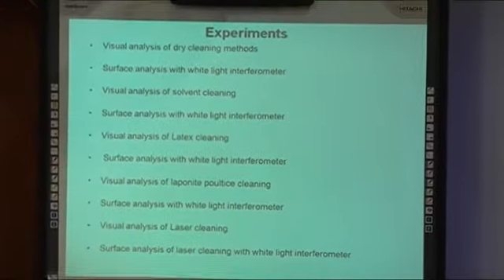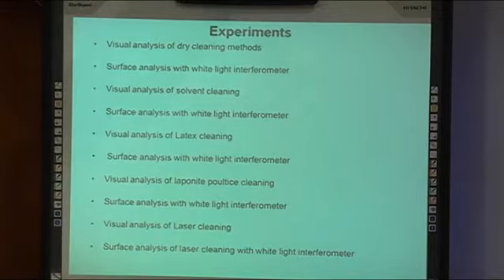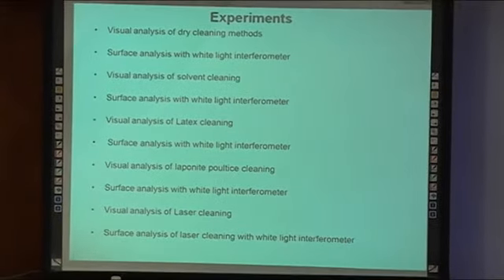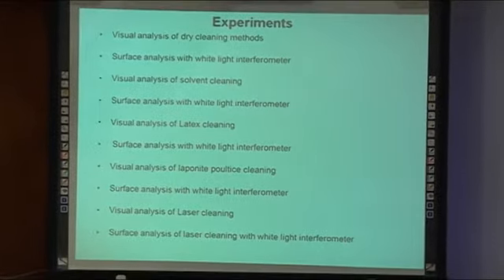The most effective cleaning method was then judged visually. Damage to the plaster surface of the effective methods were analyzed under an optical microscope. The cleaning methods found to be the most effective yet least damaging were then chosen for the next phase of the experiment, where further analysis was done using white light interferometry on pure plaster control subjected to the chosen cleaning methods.